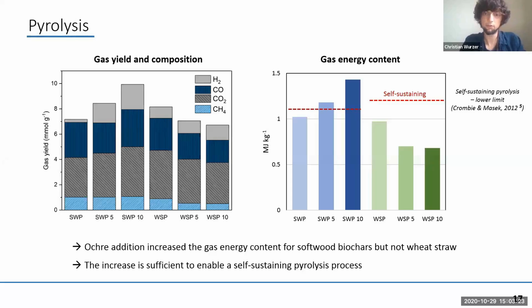In blue, the softwood biochars, and in green, the wheat straw biochars. And the red line indicates the limit for a self-sustaining pyrolysis run. That means if you directly utilize your gas stream by burning it and heat the reactor with the energy from burning your gas, you can actually self-sustain your pyrolysis if you're above this red limit, which was previously calculated by Crombie and Masek.